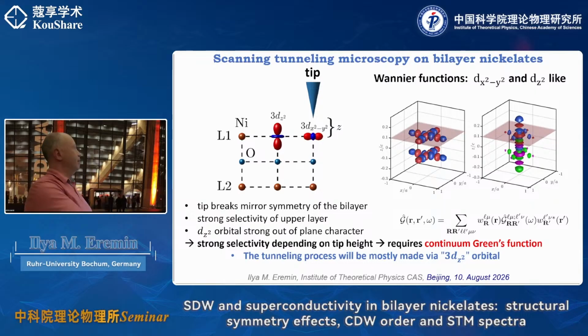Because effectively, if you look into the structure of your Wannier function, you realize that you need to extend it well beyond the central position of the nickel, and it includes all the oxygen states as well. And if you look into the dz square, you see that there is a strong involvement of the oxygen pz states, and it's a very extended object. That's the extent to which the oxygen states are important in this case. And if you would do ARPES, and this has been done, you will see a lot of contribution from the oxygen, but it is included in this effective low energy model.